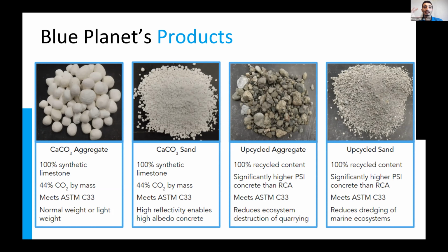But going back to that liquid that we get after processing the demolished and returned concrete, that's what you need to sequester the CO2. Once we sequester the CO2, we make our calcium carbonate product. That's the two on the left. What's nice about manufacturing a product like this is that we can manufacture it to be round, as we showed in this picture here. We're manufacturing it now to look more like rocks, with different shapes to promote tight packing, and we have a sand like we're showing here. It can be rough, smooth, oblong, depending on the concrete application. What's nice about the calcium carbonate is all the CO2 that's sequestered into it. By mass, calcium carbonate is 44% CO2.